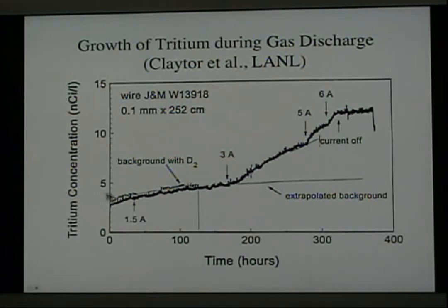So you can see that for a period of time nothing happened. No excess tritium was generated. And then when the current was increased, tritium began to accumulate. And again, when the current was increased, it accumulated more rapidly. Again, it was increased, and the rate went up. And finally, the current was turned off, and the tritium content remained constant.